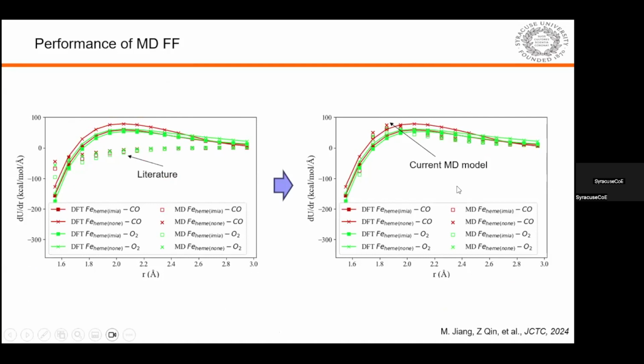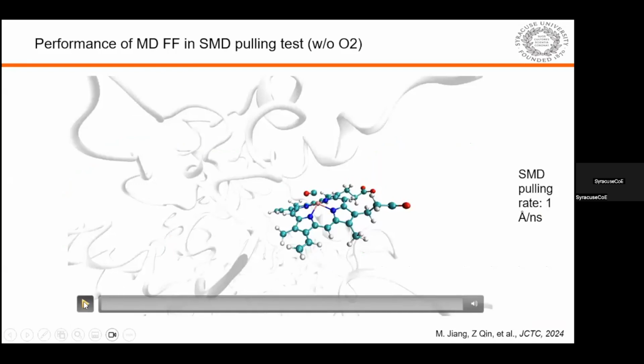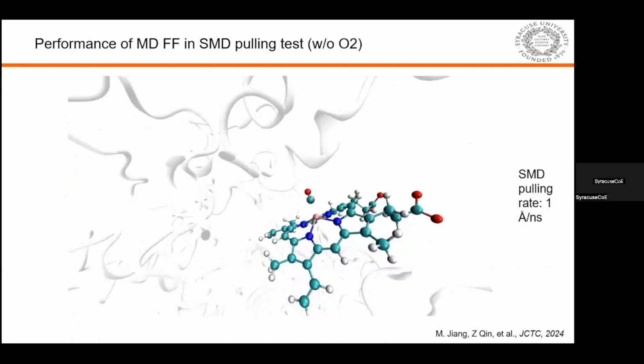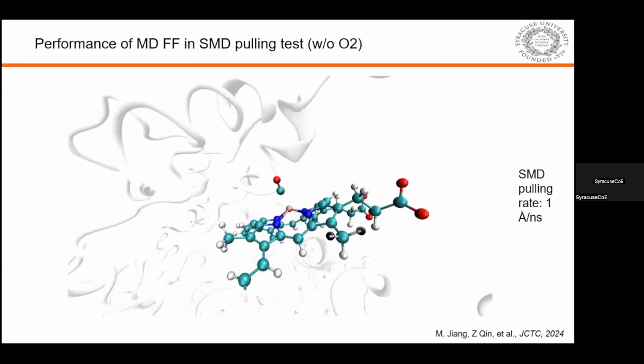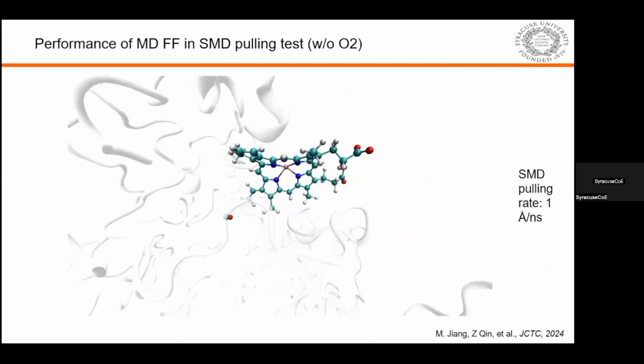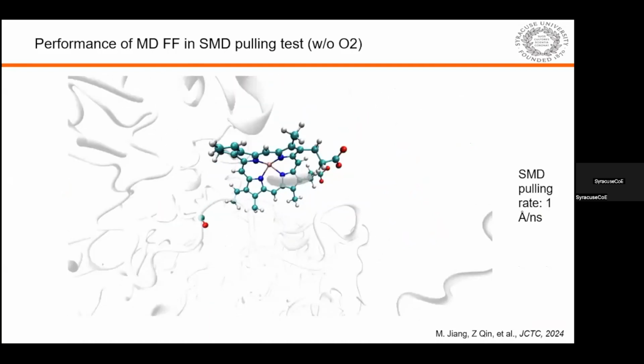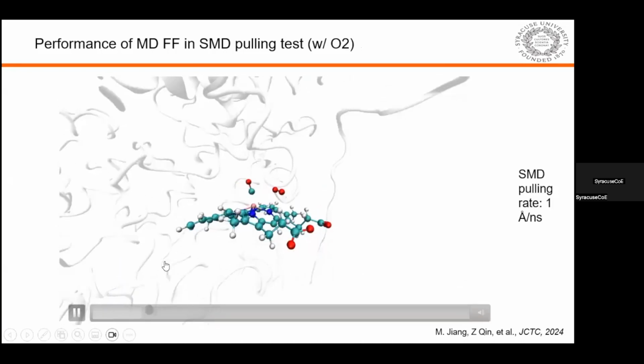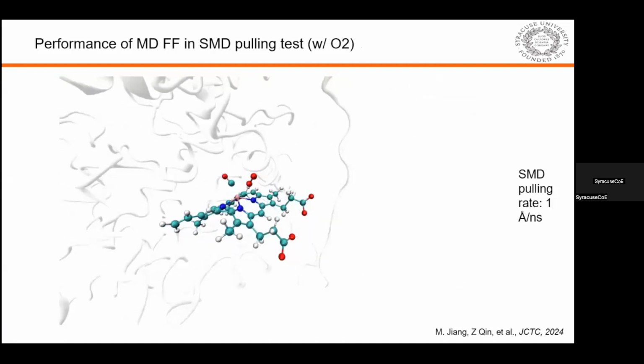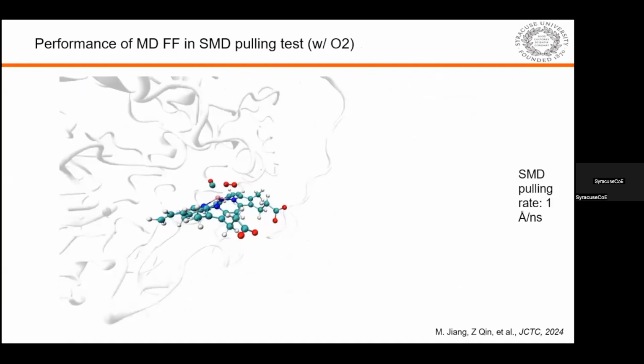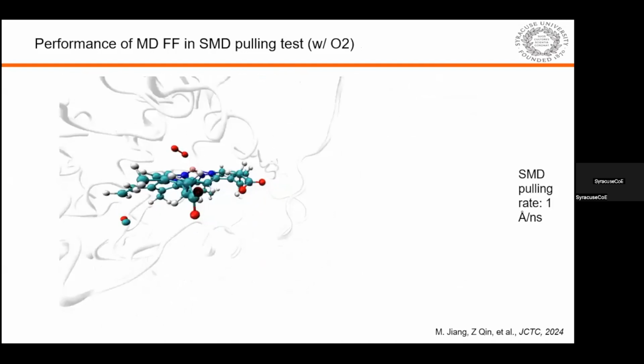So I just want to quickly show the performance of our force field. In the literature, these curves are the ab initio calculation, but the existing force fields don't agree very well with the DFT calculation, while our developed force field has a much better agreement. Using that, we can simulate, for example, a carbon monoxide bound to the hemoglobin iron atom, and then use a spring to pull it off. During this simulation, we can measure the amount of force needed to pull the carbon monoxide from the binding state. Then we put an oxygen atom close to this binding site, repeat the simulation to pull carbon monoxide away, and measure how the oxygen biases the energy landscape for this detachment.